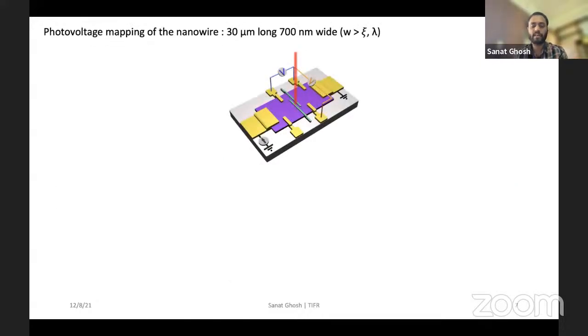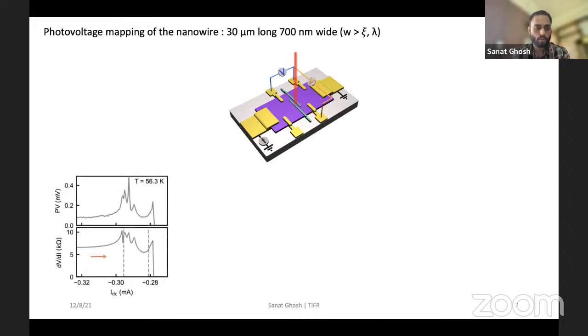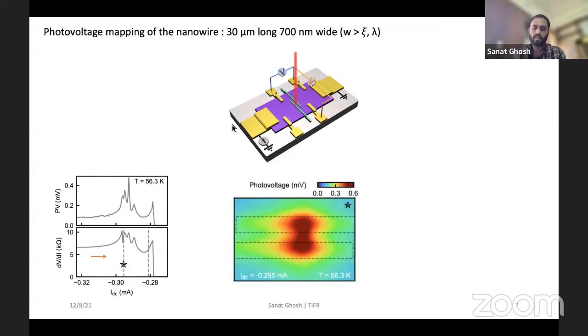Now, to visualize this, next we measure the photoresponse of the nanowire. For that, we shine a laser on the nanowire, and its intensity is modulated at some frequency, and we measure the photovoltage generated across the nanowire at the same frequency. So here you see simultaneously measured differential resistance and the photovoltage across the nanowire. Then we park the nanowire at a specific biasing current, and map out the photovoltage spatially.